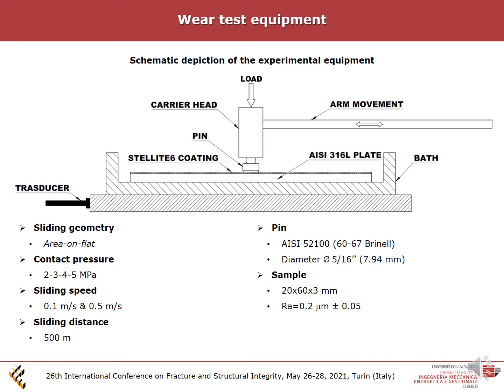The experimental tests were carried out on a reciprocating sliding test rig in dry room condition. It has temperature around 25 degrees and relative humidity around 40%. The wear tests were performed in order to evaluate the influence of the sliding speed and applied load on the wear mechanisms. And in particular, two values of the sliding speed were chosen, 0.1 and 0.5 meter per second, and four values of the contact pressure in the range from 2 to 5 megapascal. Sliding distance was kept constant for all experiments and in particular was set equal to 500 meters with a stroke length equal to